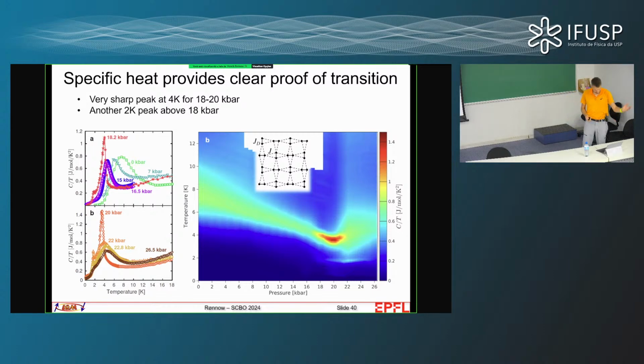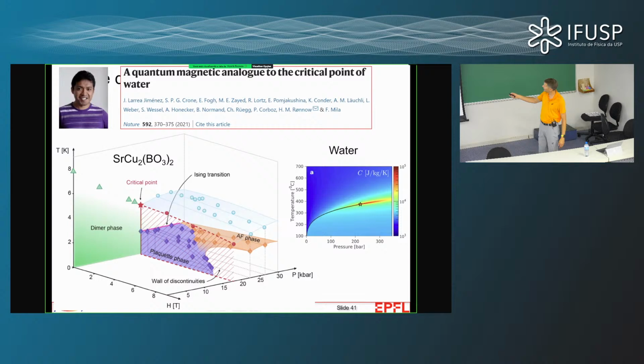Okay, so we looked at this a lot, and it was together with my theory colleague Fredrik Mila that we figured out what is really happening. And actually the answer is here. It's just the same as water. You take water at ambient pressure, you heat it up to 100 degrees, it evaporates into vapor. You apply a pressure of 100 bar, you have to heat it up to 300 degrees before it vaporizes. If you apply a pressure of 200 and something bar and you heat it up, then you go from having the liquid phase to having vapor phase without ever having a phase transition. This phase transition has a critical endpoint happening here, and so you can go from water to vapor without ever crossing a phase transition.